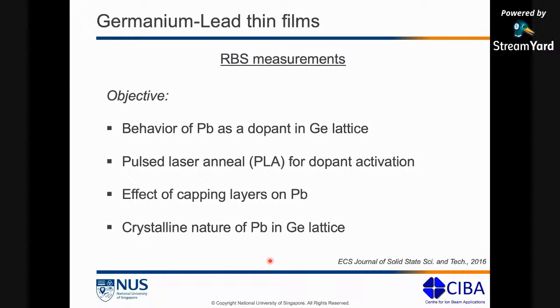So if you want to make it into a direct bandgap semiconductor, we need to dope it with impurities like lead and tin. And so what we were trying to do here was to see how lead as an impurity dopant behaves in a germanium lattice. So we had these germanium lead thin films that were sputter deposited, and we wanted to see whether a pulsed laser annealing process works as a dopant activation for lead in germanium. And what we also wanted to see was whether lead stays in the germanium lattice, or whether lead moves in the germanium lattice, whether it moves towards the substrate, or whether it moves away from the substrate.